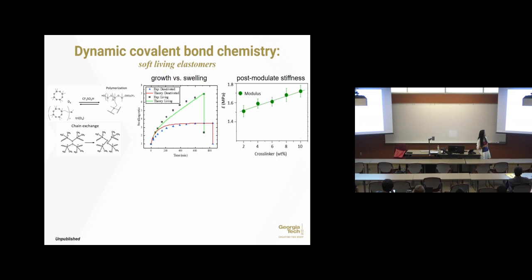And you can see, indeed, it follows our prediction. When we turn off this dynamic bond exchange reaction in the material, it just swells, right? This red line is prediction, and the dots are experiments. So it swells only to a certain extent. And then when we extract all the solvent out, it comes back to the original size and shape. But if we turn the exchange reaction on, then it keeps swelling. It keeps becoming bigger. And if at a certain point we extract out all the solvent in it, you see this polymer becomes bigger than the original one. So the monomer is really incorporated onto the main chain.